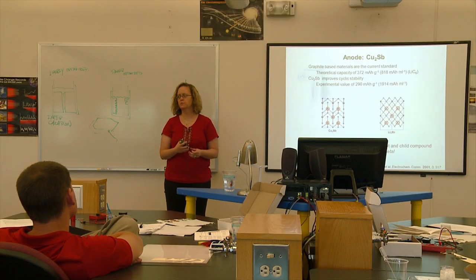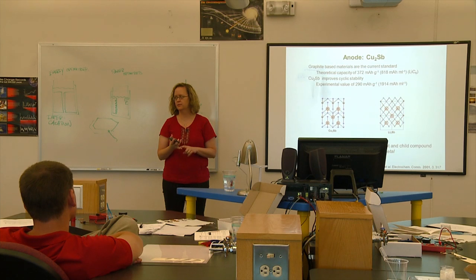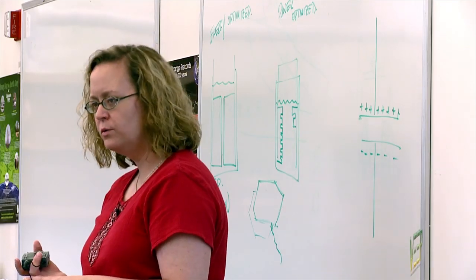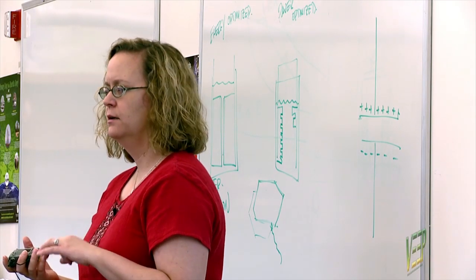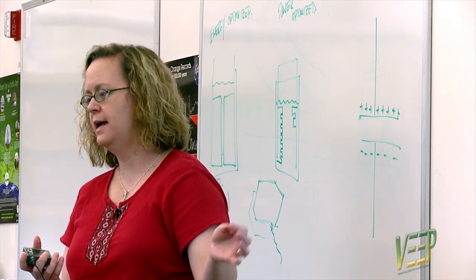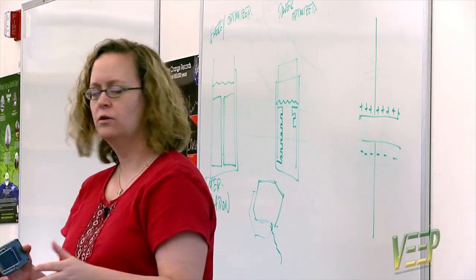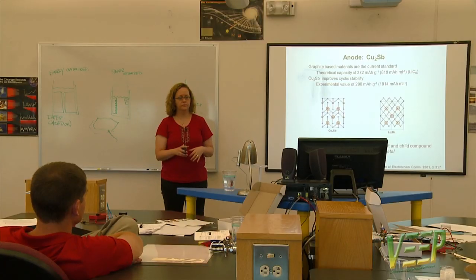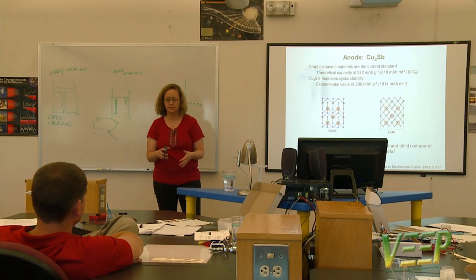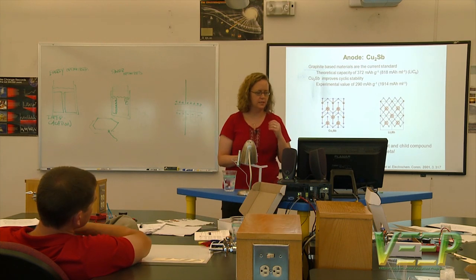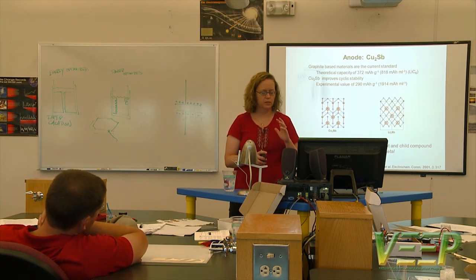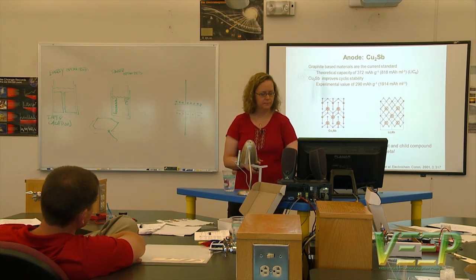So did you guys talk at all this morning about lithium fires or shorting? Anytime you see in the news a recall on batteries, like the big Sony recall, or fires like the FedEx plane that went down because of the lithium ion battery pack, that's almost always because of lithium metal causing a short. So we can't have that in our battery because everything's too close. So we picked an anode that chemically can't plate lithium metal so that we could make it safer. The other good part about this material is that it is really conductive, so it dissipates heat really well.